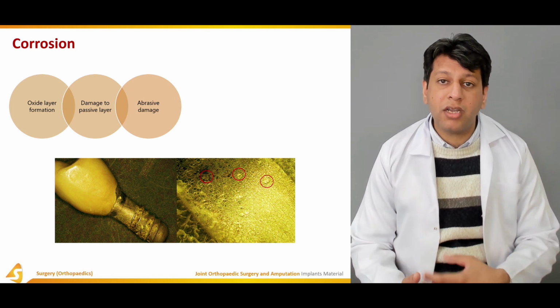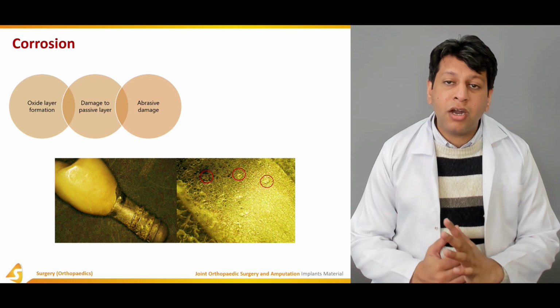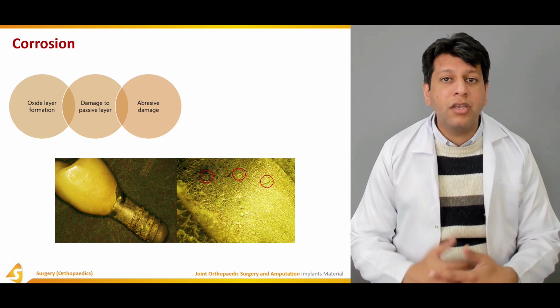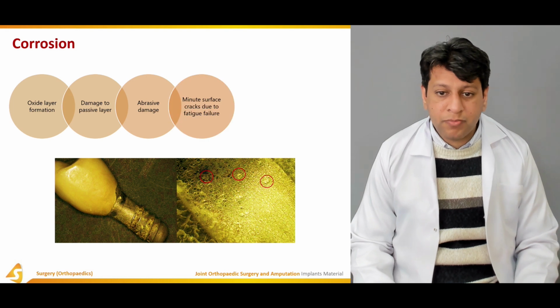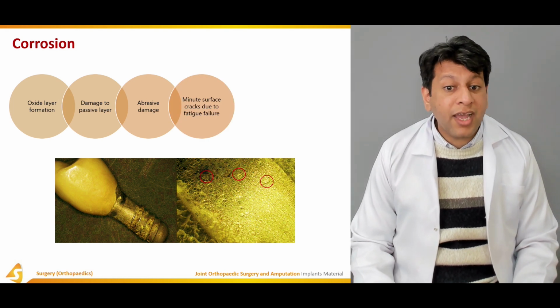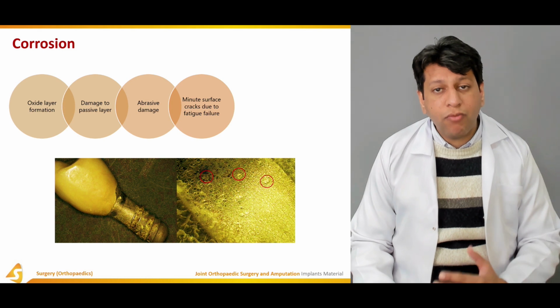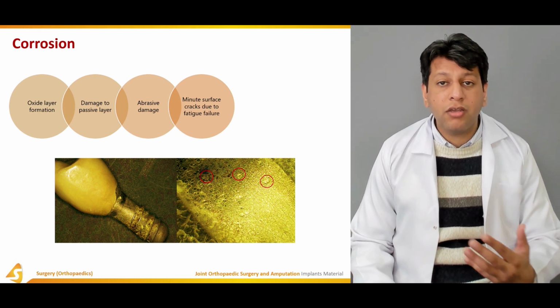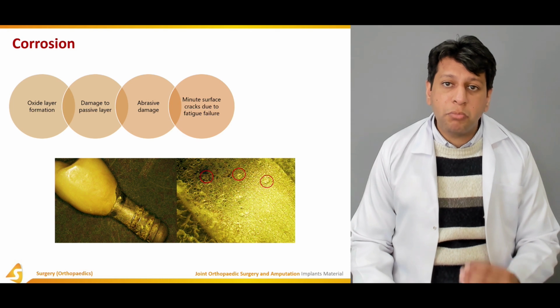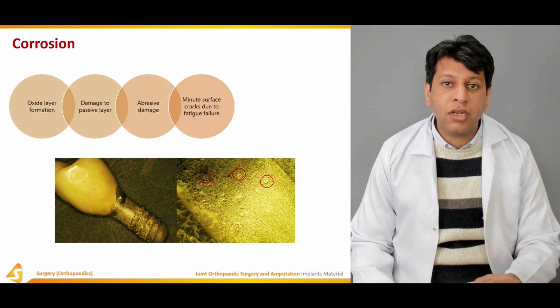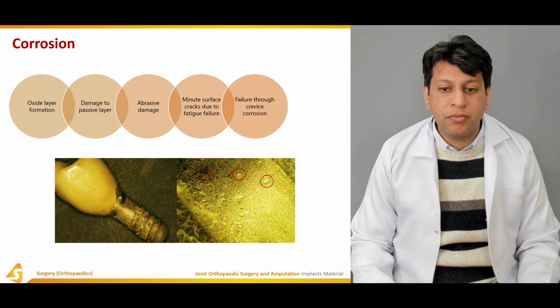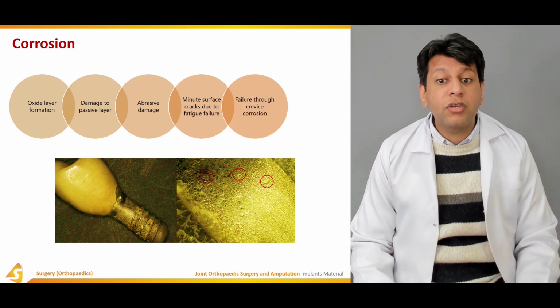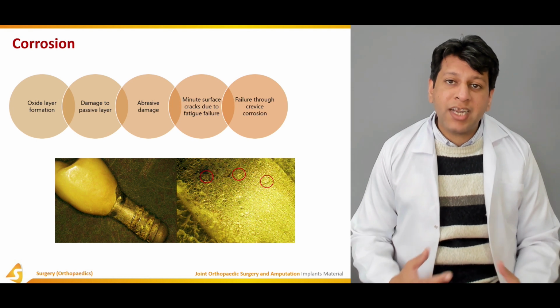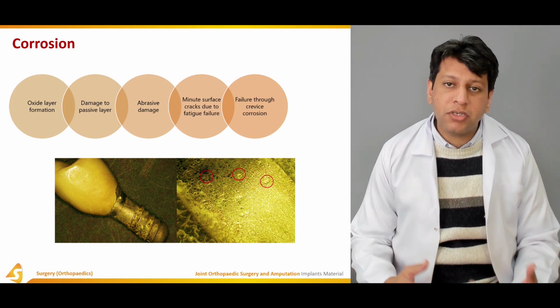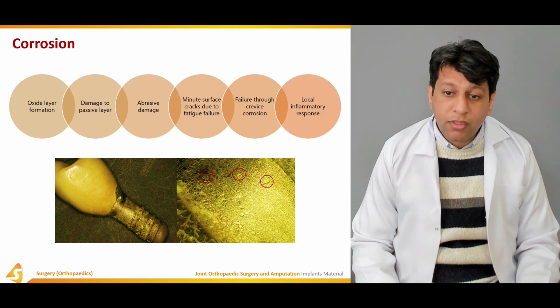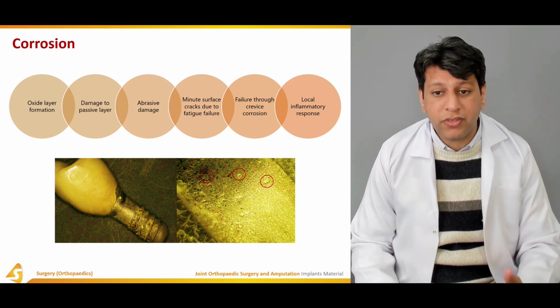For example, in the case of metal on poly, the polyethylene is articulating during the normal cyclic loading, leading to wear and tear or abrasive damage. This could be minute surface cracks due to fatigue failure. Over the years, with constantly repeated cycles of loading and unloading, this may produce cracks, and eventually through these cracks, oxygen can seep in, leading to corrosion. Or failure through crevice corrosion. Crevices are actually cracks which appear in the surface, and once they get oxidized, this leads to corrosion. This whole process is termed crevice corrosion.